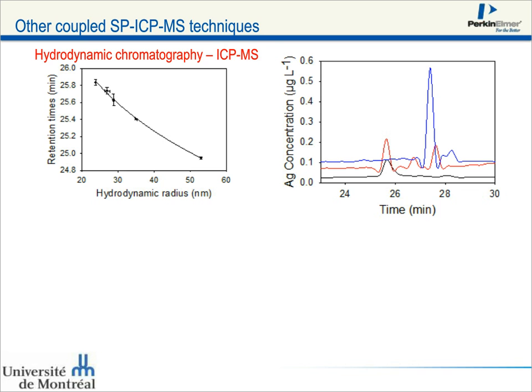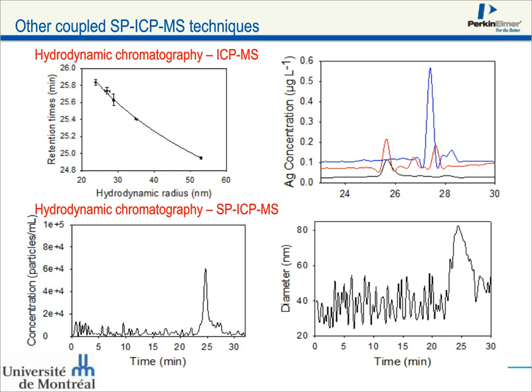So we have an additional advantage by switching into single particle ICP-MS mode. Not only will we get information on the concentrations, we get information on the particle numbers on the lower left, and some independent information on the particle diameters. So information on the particle diameters from the retention times, but also information from the single particle ICP-MS, albeit with slightly higher detection limits. So that's what I've got to say for now.